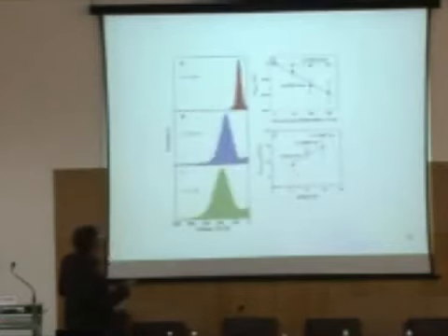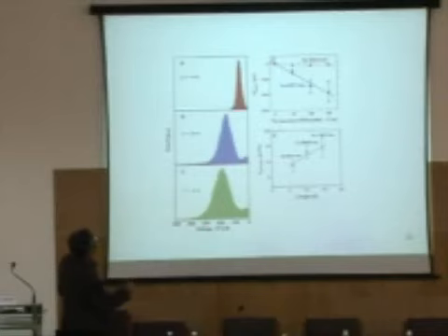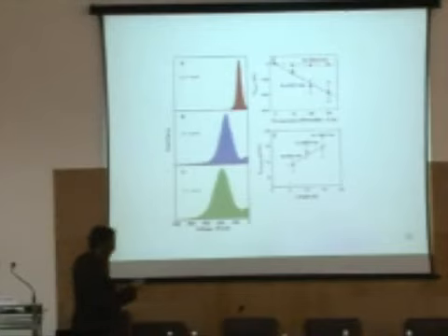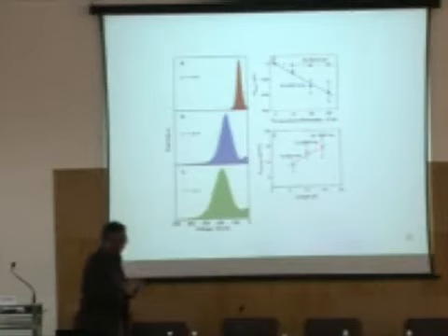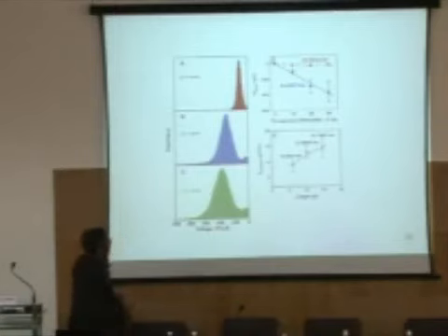And of course, these are single-molecule experiments, so they had to do thousands or millions. These are statistics. As you can see, as the delta T changes, this whole thing moves. And they also measured the voltage as a function of temperature. From there, they could figure out the thermopower. It's not big. It's only about 10 microvolts. But who knows? Maybe I can put a beautiful array of these molecules nicely ordered, which is possible by self-assembly. I can get a much bigger response out of it.